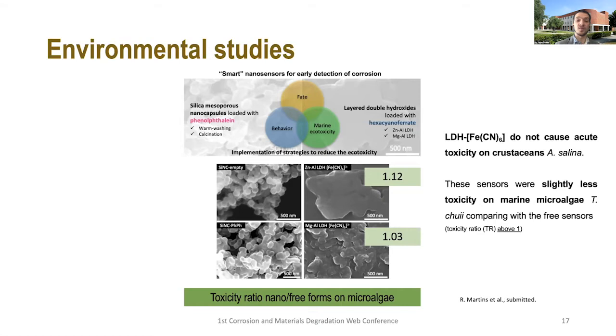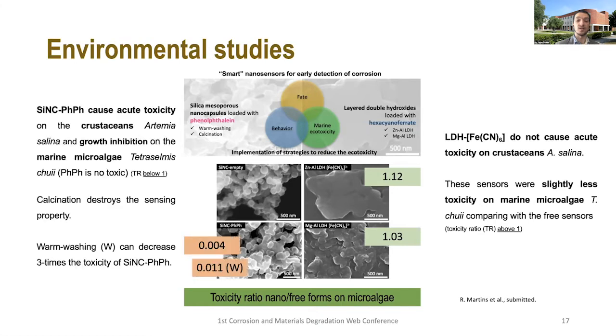But for phenolphthalein, we found different results. We saw that the silica phenolphthalein capsules were inducing more toxicity than the free phenolphthalein. And this was ascribed to the presence of remnants of the surfactant from the synthesis. And we could not remove the surfactant. We could try to use washing, but we could not calcine the silica. Otherwise, we would also calcine phenolphthalein, which is also an organic compound, and we would lose the sensing ability.